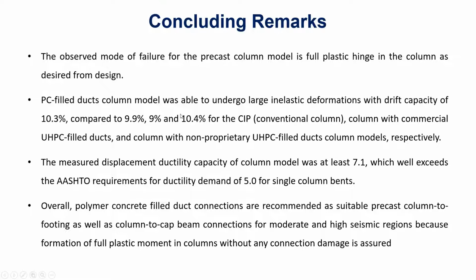So this confirms that polymer concrete works almost as well as UHPC. The measured displacement ductility was at least 7, which exceeds the AASHTO requirement. For a single column bent, it's 5. For double column bents, it's 6. So the 7 exceeds both anyways, although only the 5 will be applicable in this case.